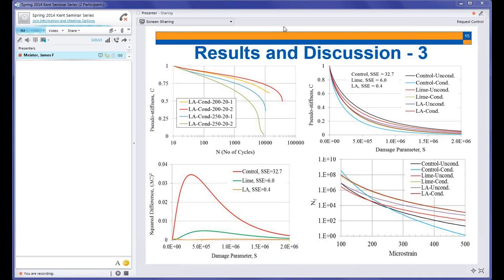Similarly for the lime, the number of cycles to failure for lime conditioned mixes is higher than for the lime unconditioned mixes. This is a misleading finding too. So what's the issue here? It seems that in order for this test to be representative of what's going on in the field, we need to run it in stress control mode, not strain control mode. Because what's really going on in the field is that we are applying stress after stress after stress on the pavement. We're not applying strain. And I know this is a big debate in fatigue testing. But for this test, to give us at least a good prediction of the performance in the field, we need to consider that.